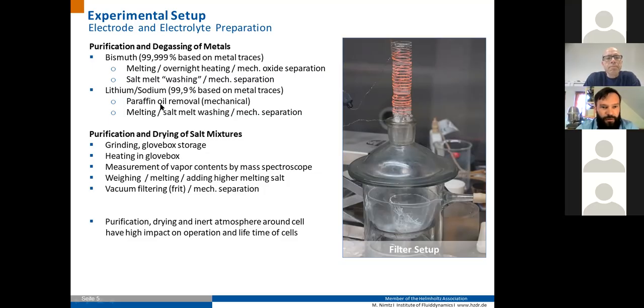Here the state how the lithium or sodium is shipped is usually covered in paraffin oil, which has to be removed mechanically by scrubbing it. And then the preparation steps are the same: melting, removing oxides mainly by contacting with fused salt, and also mechanical separation of possible impurities. The salt mixtures